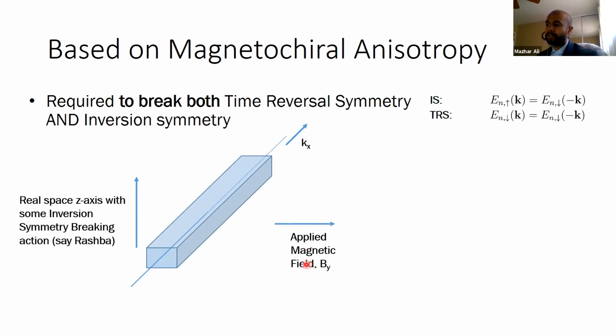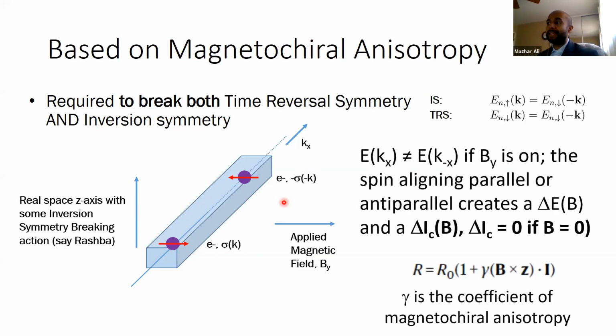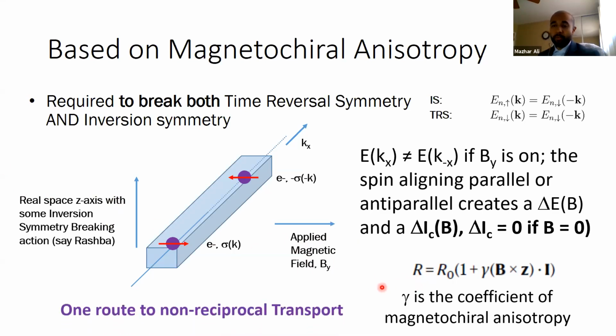So this one broke inversion. Now we're going to break time reversal along the y direction. If we imagine two electrons in here, the electron at plus k is not the same as the electron at minus k, because they can have different spin orientations, either aligned parallel or anti-parallel with the magnetic field. And that will result essentially in an energetic difference between the plus k and minus k electrons, which will then result in a difference in critical current for, let's say, positive x versus minus x. But again, that's only true if the magnetic field is on, because this whole system works by both breaking time reversal and inversion. So this is one route to non-reciprocal transport, to making right not equal to left. But that's not what we're going to be using today, but it's important to know that this exists.